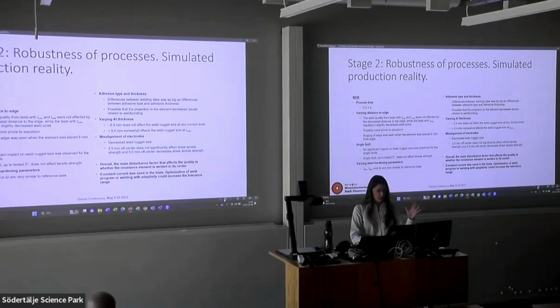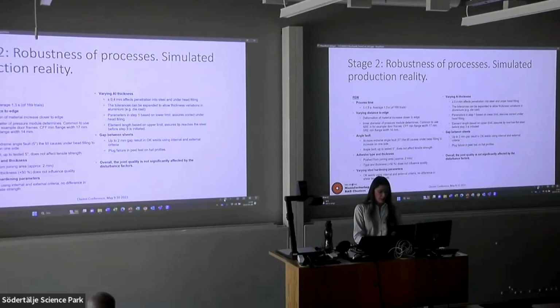So from the resistance element welding, what we can say is that the misalignment of the electrodes is the main issue when it comes to this method. For friction element welding, overall the joint quality was not significantly affected. In those cases that we did see some sort of effect, there are often adjustments you can make in the process itself, if they are known to you, that can help you overcome these issues.